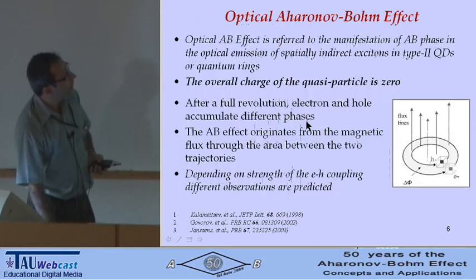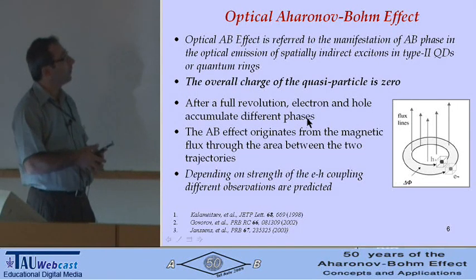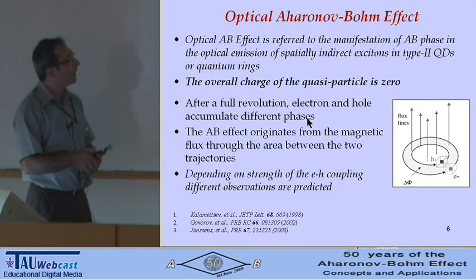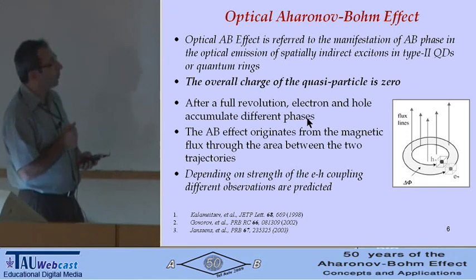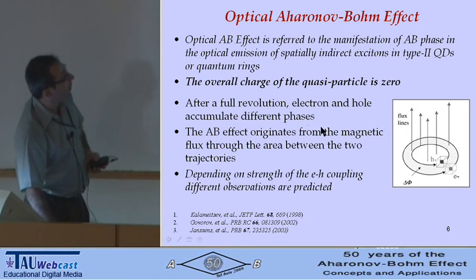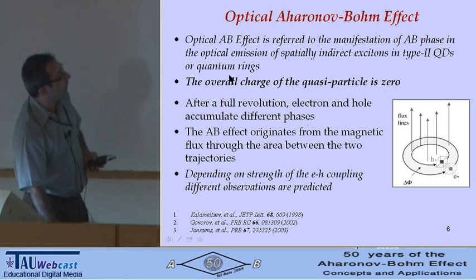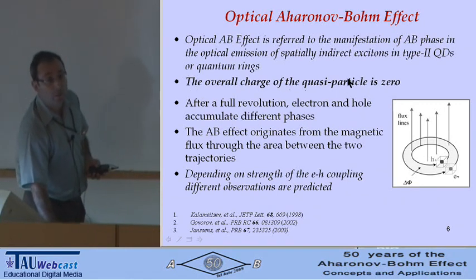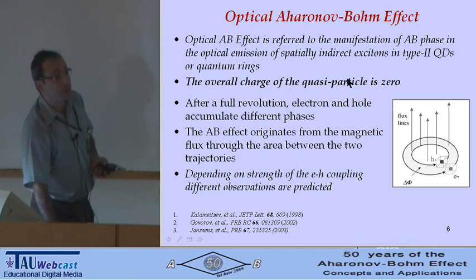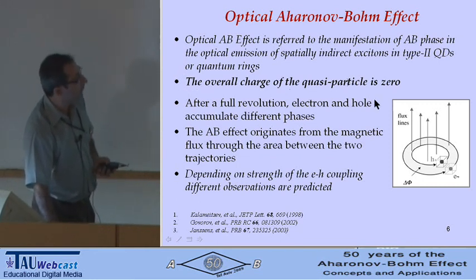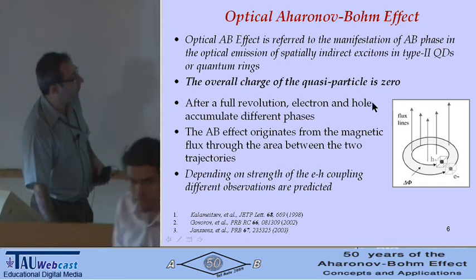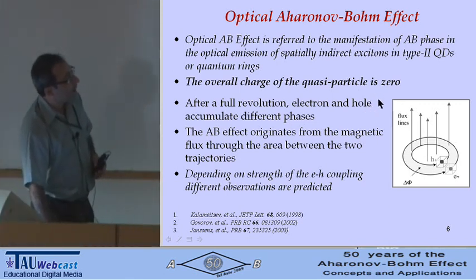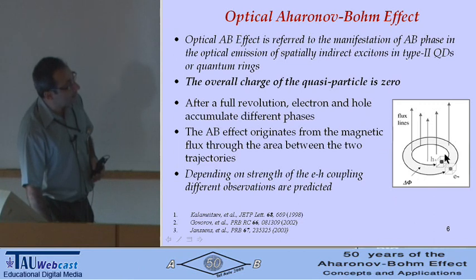cylindrical symmetry. So what we understand by the optical Aharonov-Bohm effect is basically a manifestation of the Aharonov-Bohm phase in the optical emission, spatially indirect exciton in type 2 quantum dots or quantum rings. What's important is that the overall charge of this quasi-particle is 0. However, you have an electric dipole which interacts with the vector potential, and you're supposed to have Aharonov-Bohm oscillations. The difference is that it oscillates with the periodicity of the flux between the electron and the hole orbit.